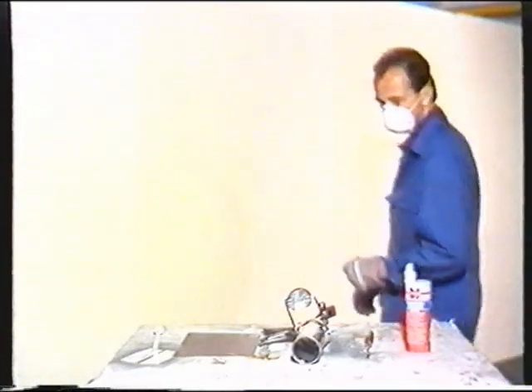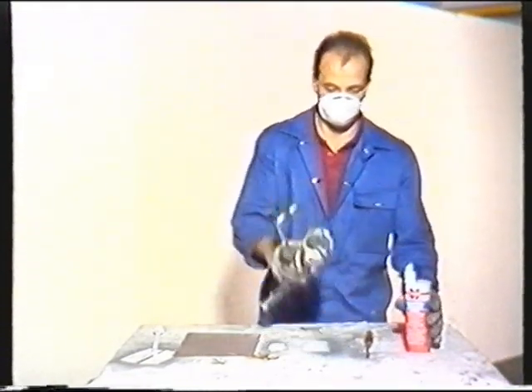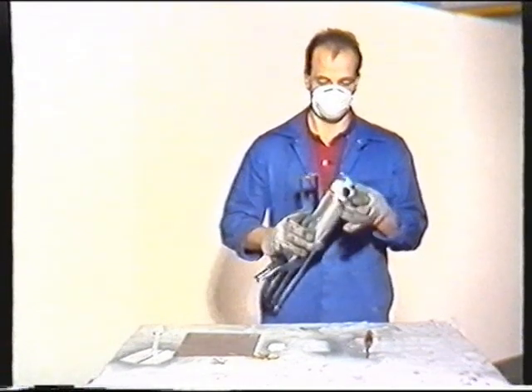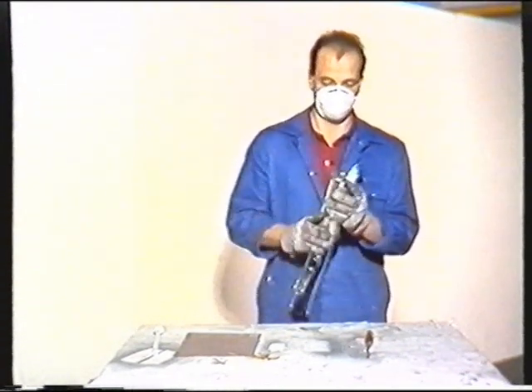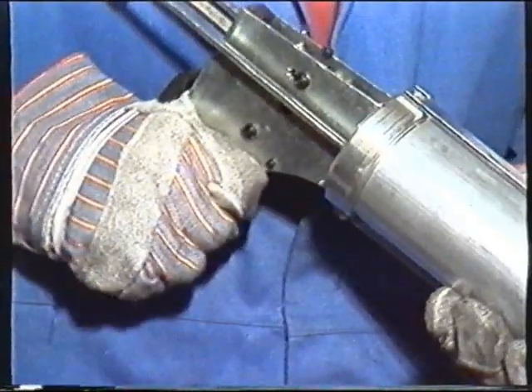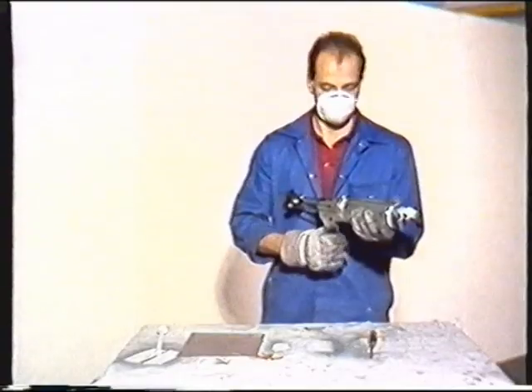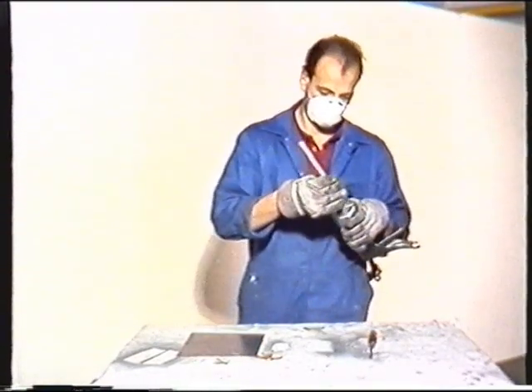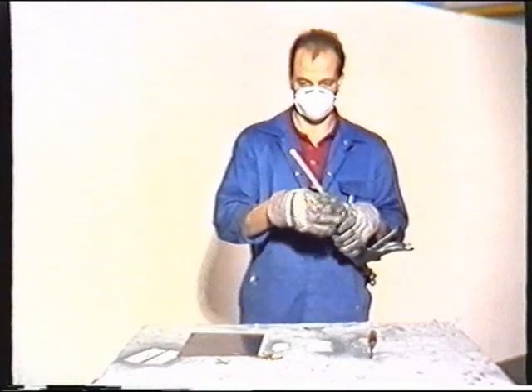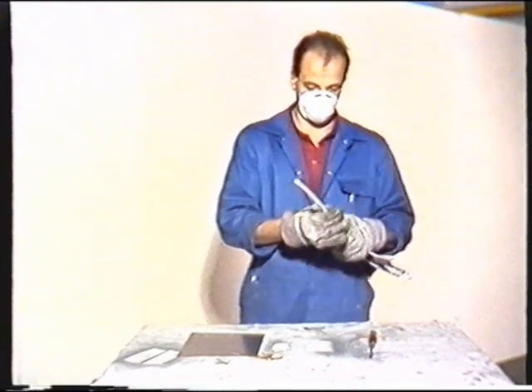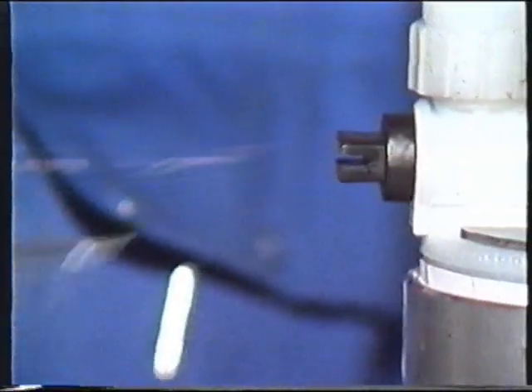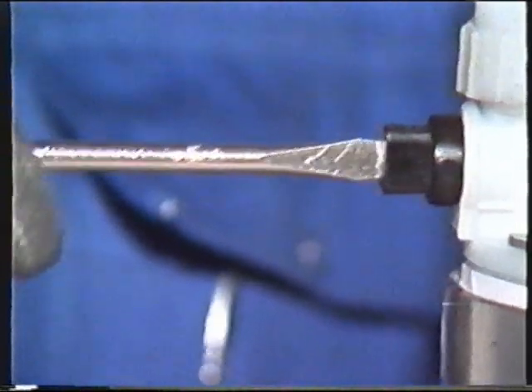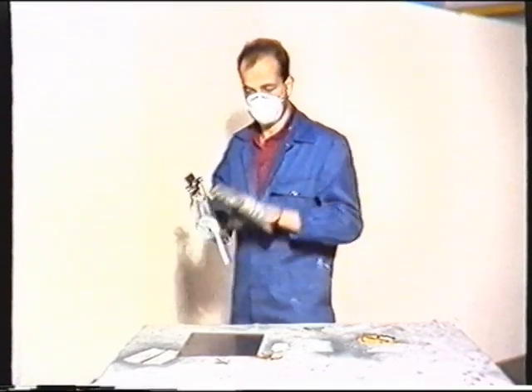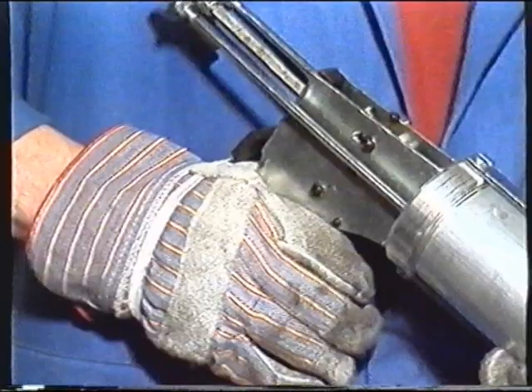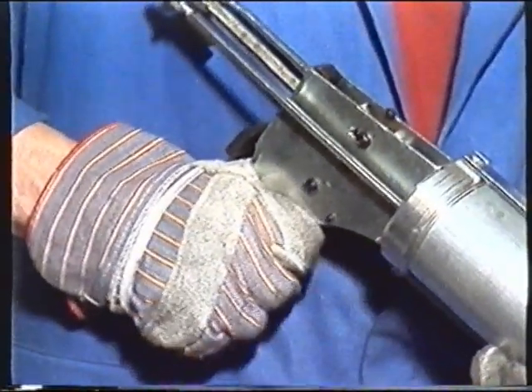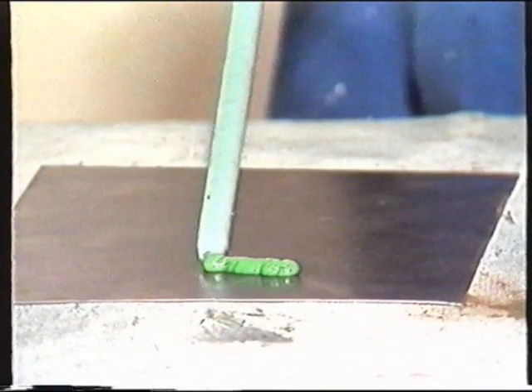It's always important to choose the right adhesive for the job. A thixotropic material is required here, which will not run out of the seam. Single-component adhesives require very high curing temperatures, which can usually only be achieved in manufacture. Two-pack materials like this epoxy cure by chemical reaction and are thus more suitable for use in a repair situation. The adhesive is mixed automatically in the correct proportions as it comes through the nozzle.